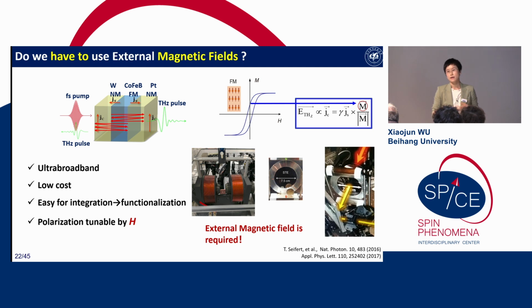The other thing is that, since I have been working for the last 10 years on generating strong field terahertz, I am always thinking that if we use a 4-inch emitter and extend the beam size, we can also get strong field terahertz. How about 8-inch? And we can get even larger facility lasers. We just directly change the window of the vacuum chamber, and then we can get the terahertz from the spintronic emitter, and you can also use the residual femtosecond laser, because the residual pump spectrum did not change, but lithium niobate cannot do that. So if we just enlarge the spintronic terahertz emitter size, a lot of problems may come. The magnetic field distribution may not be uniform there. So can we try to find a solution that does not use an external magnetic field?